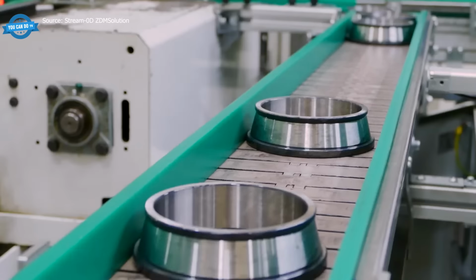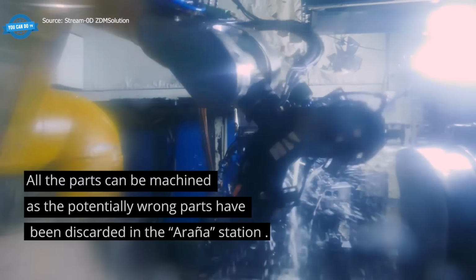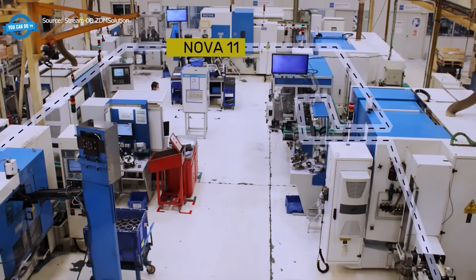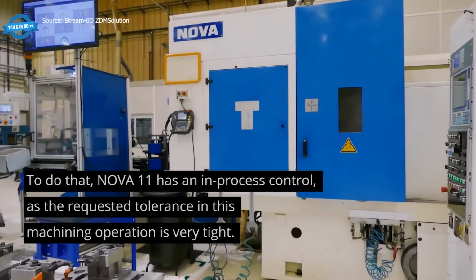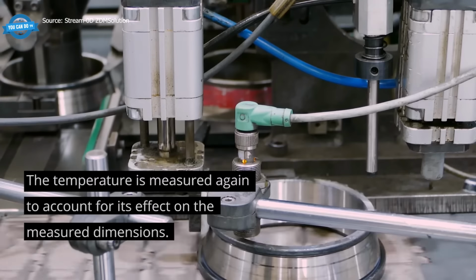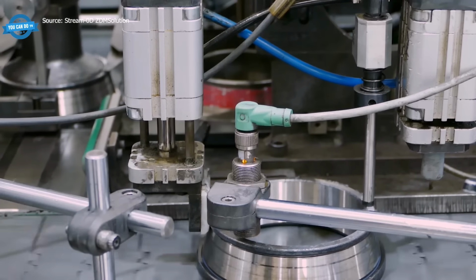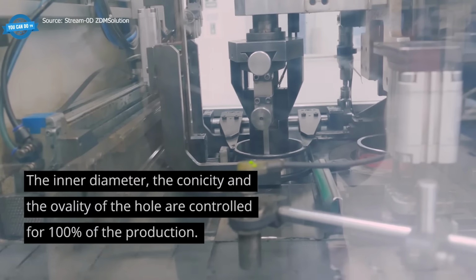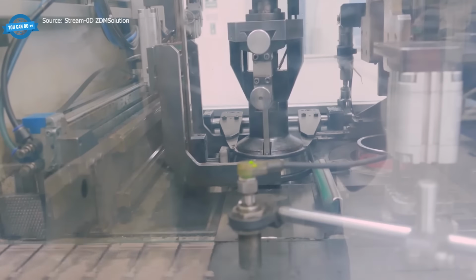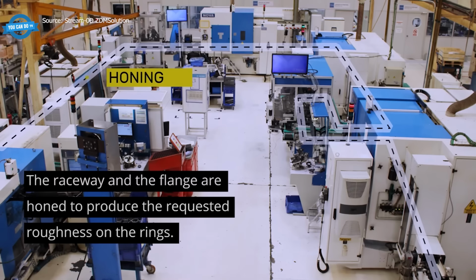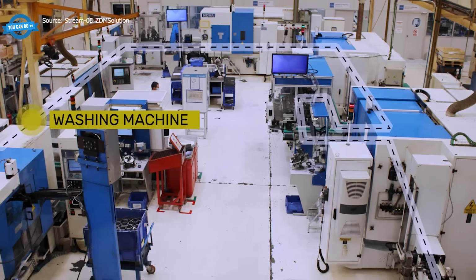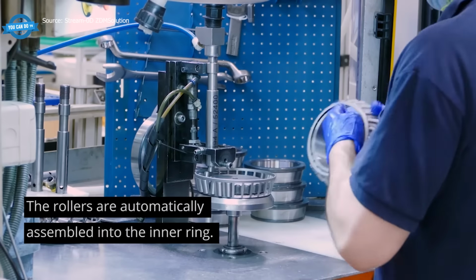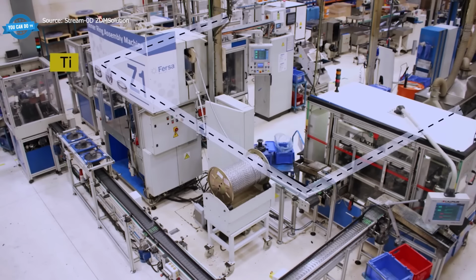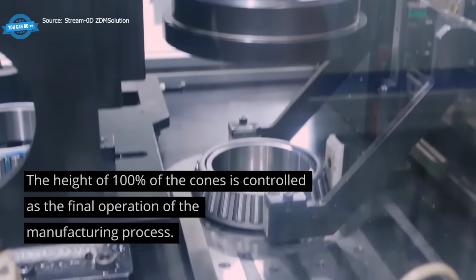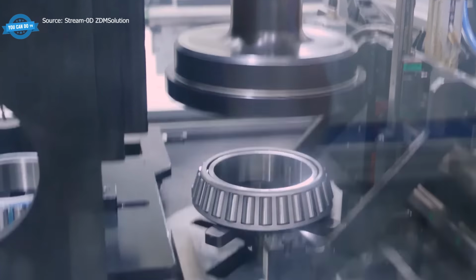Inner diameter is ground with in-process control because the tolerance window is too narrow for end-of-line inspection alone. Temperature is measured continuously to compensate dimensional drift caused by thermal expansion. Inner diameter, conicity, and bore ovality get 100% checked. Adjustments feed back automatically to the grinder. Final cone assembly height is checked on every unit by robotic gauging.